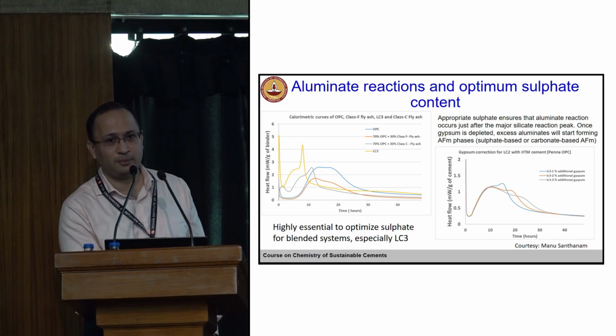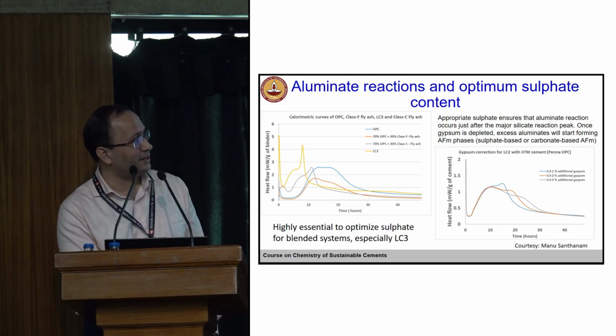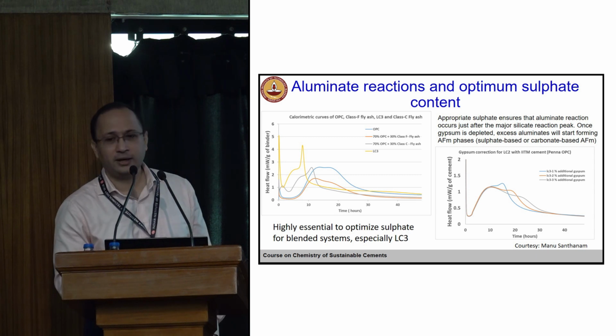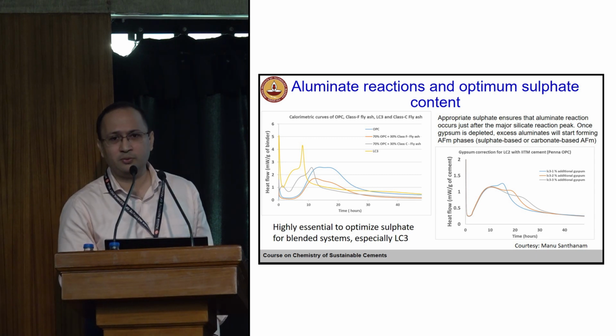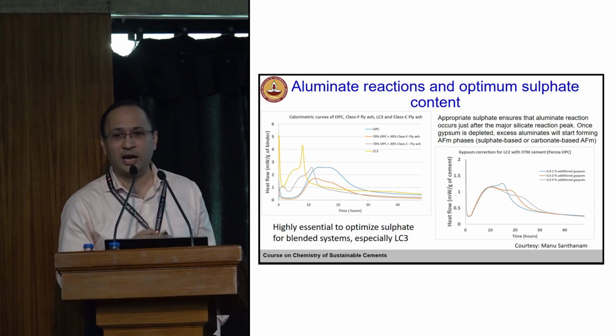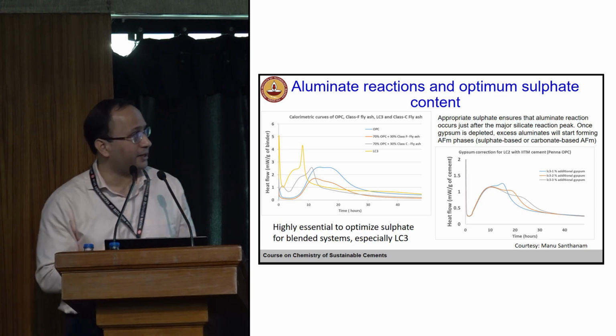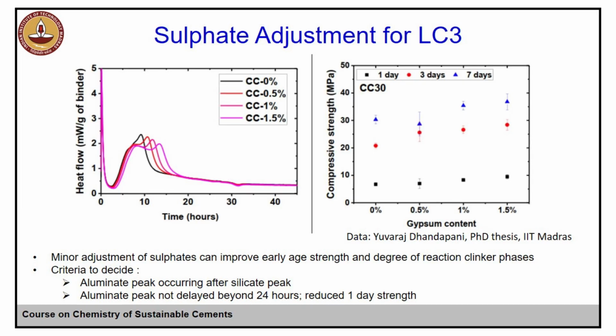Silicate hydration is very, very important, right? So it should come after that. So beyond a certain percentage, then we know that, okay, now it's fine. So this could be one way to also optimize the sulfates in the systems where you have more alumina, from SCMs, which would be the case when you have fly ash, calcined clay, or metakaolin.